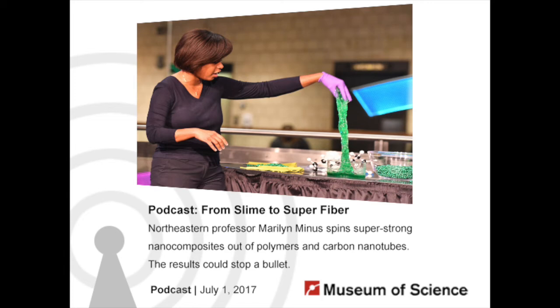So what's the next step after textiles then? After textiles are the super fibers, or high performance fibers, as we also call them. These fibers have almost 80 to 90% of all the polymer chains aligned. Oh, okay. And so when we align more of the polymer chains, now you're pulling on the chain itself. Those fibers are really, really strong. And those are our bulletproof fibers and the fibers that we use in aircraft and spacecraft and cars.